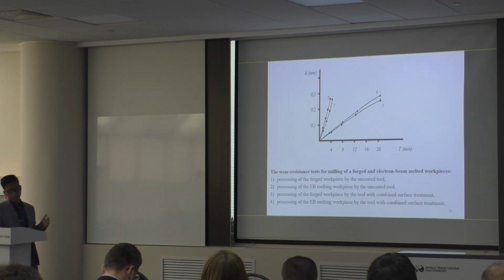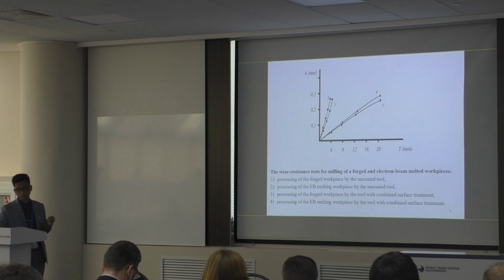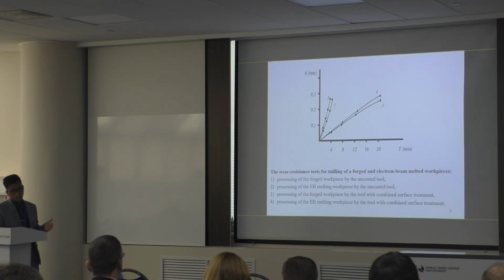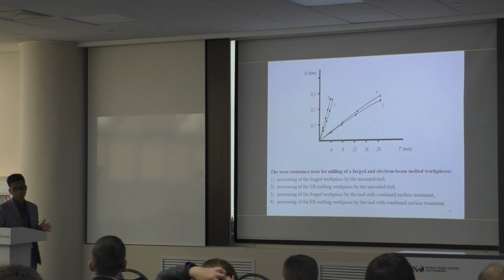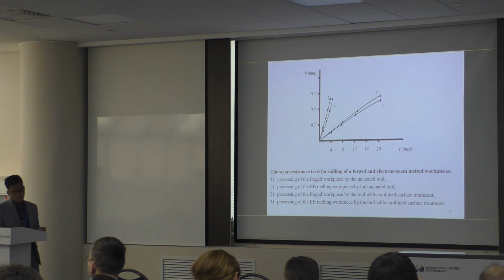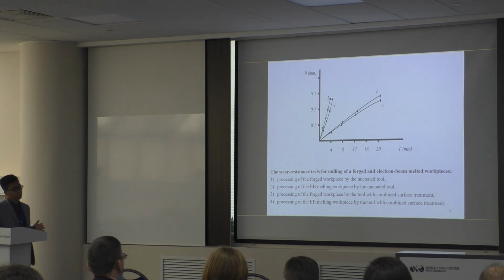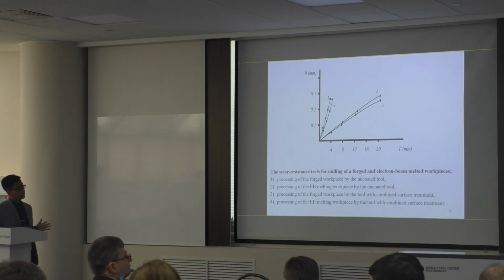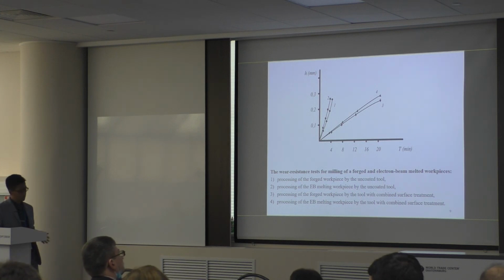As a result of complex processing, the characteristics of the contact process change, which reduces the intensity of the heat source near the cutting edge of the tool. The stability of the cutting edge shape increases. The modifying layer continues to perform a productive function even after the damage of the coating, which affects the wear of the tool.